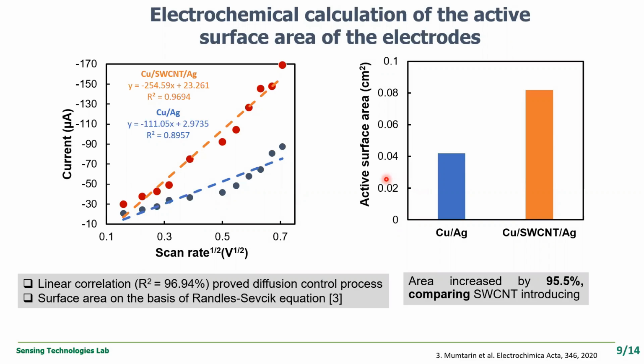And now the electrochemical calculation of active surface area. We applied different scan rates ranging from 25 millivolt per second to 500 millivolt per second for both sensors, and plotted the square root of scan rate versus current. From the linear correlation, it is proved that in both cases there are diffusion controlled processes, and the surface area has been measured with the help of the Randles-Sevcik equation. The result is plotted in this graph, and the surface area of the copper silver electrode is 0.04 centimeters square. After incorporating single wall carbon nanotube, the surface area of this copper CNT silver sensor is 0.08 centimeters square, which was a 95.5% increment.